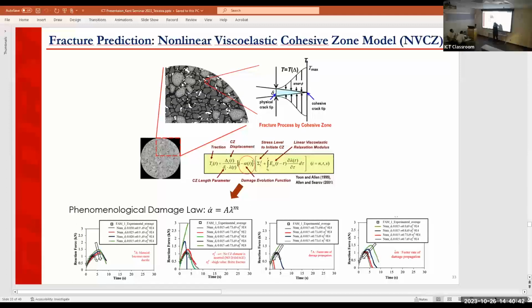And we have several parameters. But one of the parameters is this alpha function. Alpha is an internal state variable that is going to count how the crack is going to propagate, how fast. In this particular study, we use a phenomenological damage law where the time derivative of the alpha function can be defined by this power law. So we have A and M as damage parameters.